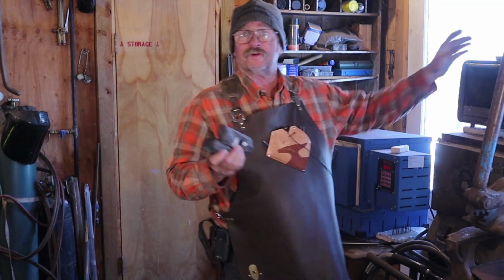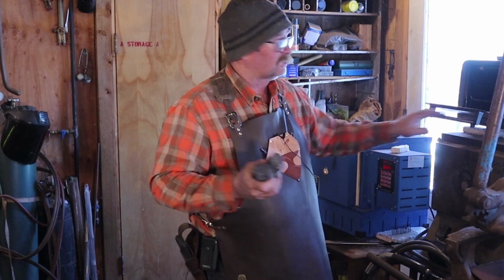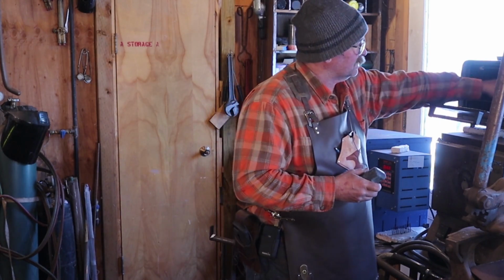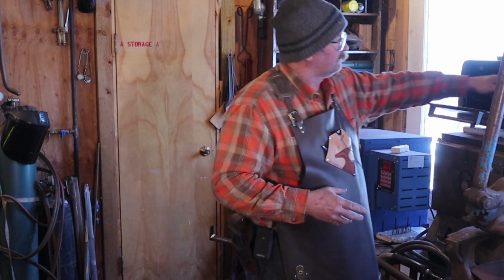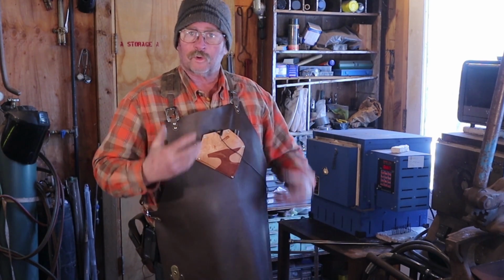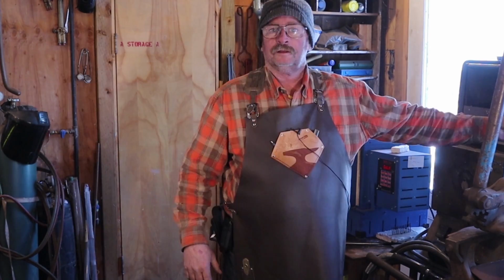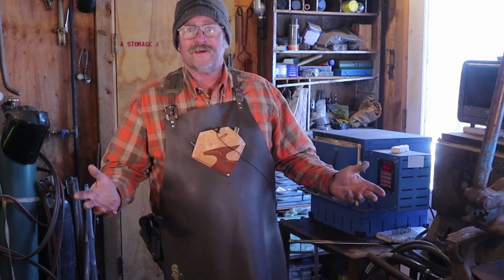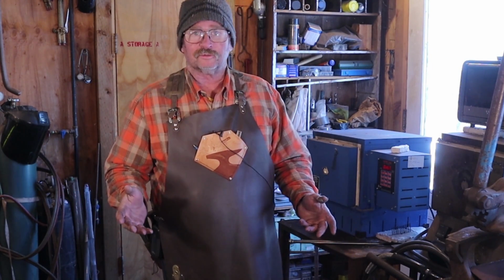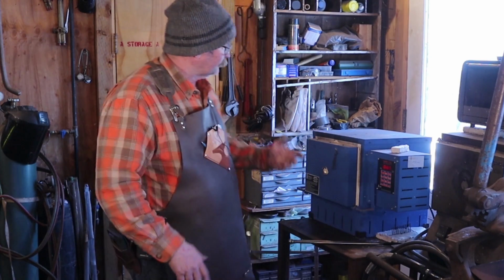And again, this is a very easy, largely hands-off process. I put them in a toaster oven, set at 450, which in this case is the ideal temperature for what I want to do with these hammerheads. This toaster oven has a timer. I set it for an hour. I ignore it. In fact, this whole hardening and tempering process is largely hands-off